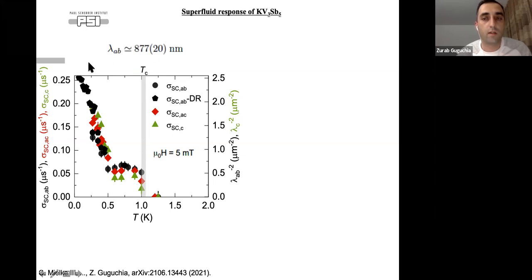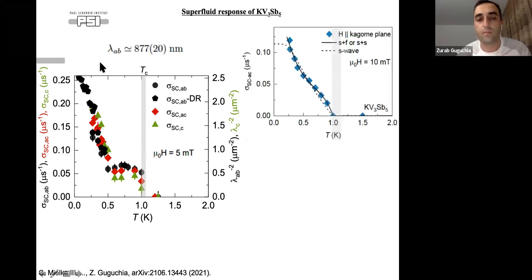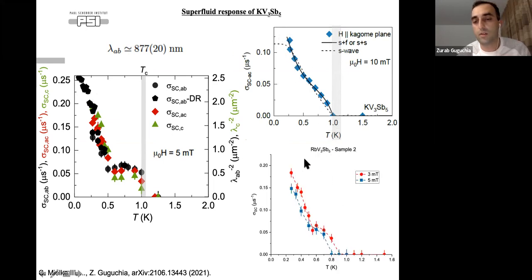And we have relatively large penetration depths. So when you apply 100 Gauss, you basically smooth out this behavior here. So it's not any more sharp, but you still have this two-step temperature dependence. And it's also similarly true for the rubidium compounds.